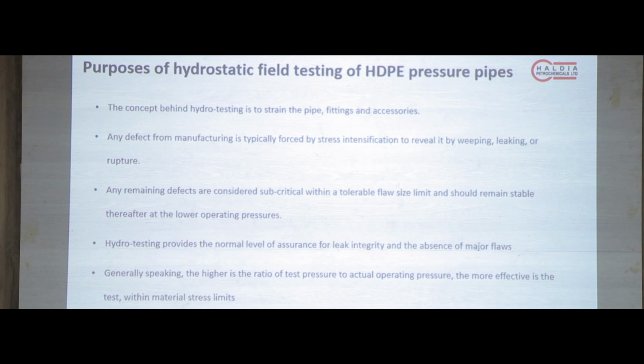During the service life, that should not lead to failure of the product. So any defect from manufacturing is typically forced by stress intensification, which I was mentioning earlier. If there is any defect during manufacturing, that shows up, or that point acts as the weaker point, known as the stress concentration point, where the stress is concentrated, and that leads to premature failure. Any remaining defects are considered subcritical within a tolerable flaw size. Hydrotesting provides the normal level of assurance for leak integrity and the absence of major flaws.